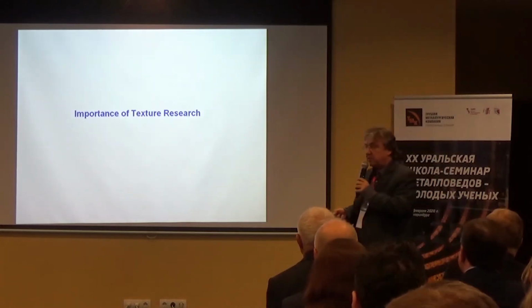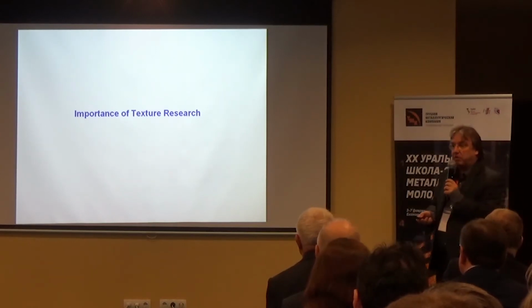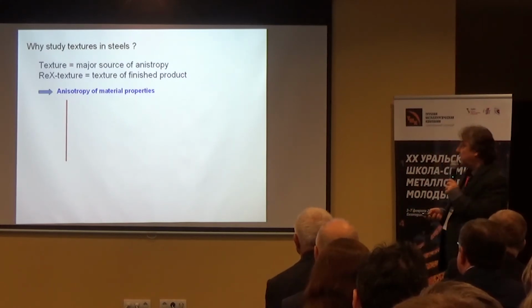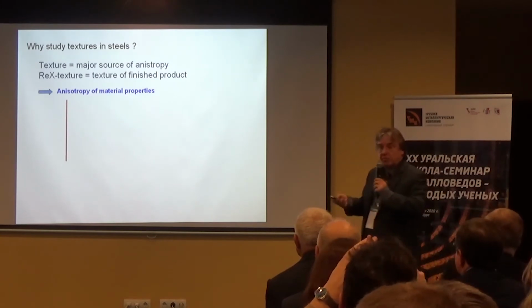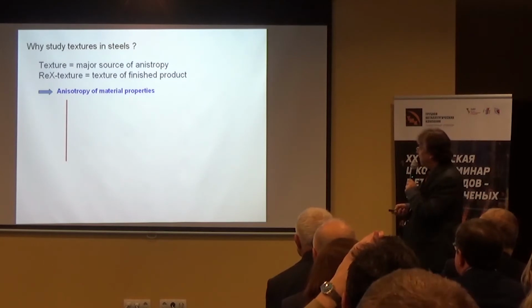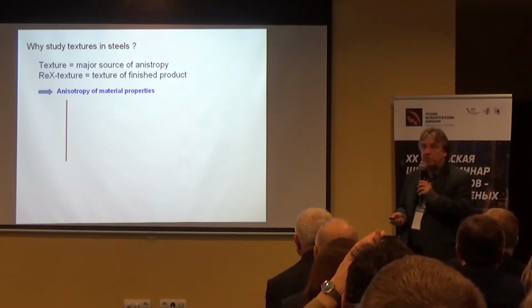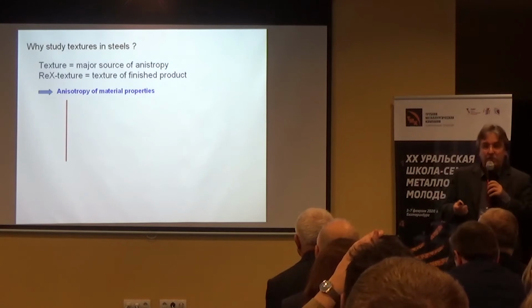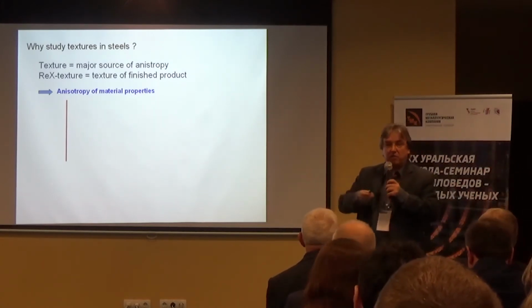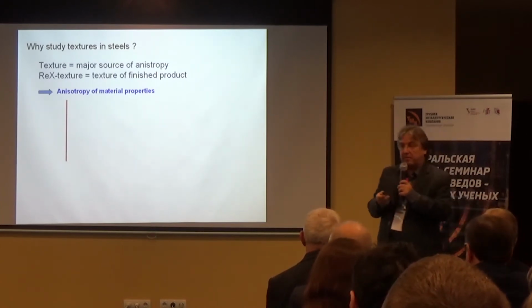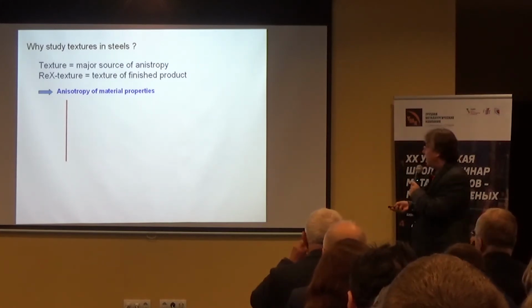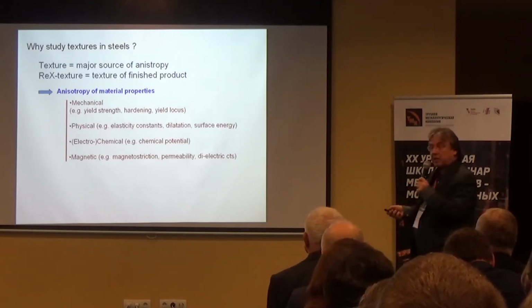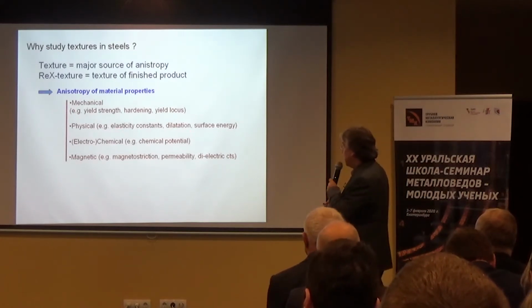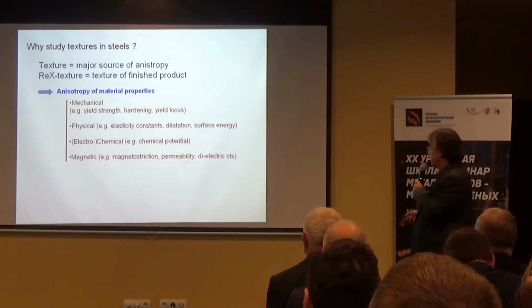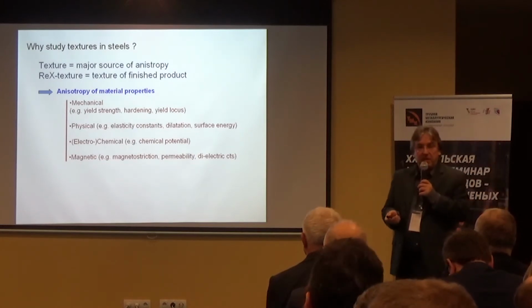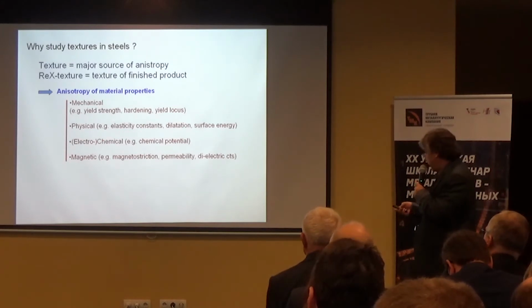Let me first start out with illustrating what is the importance of texture studies. Why do we still study texture in steel? Or in other metals, of course. Texture, in the first place, is a major source of anisotropy. So very often material properties have anisotropic behavior. If you, for example, measure the strength in the rolling direction of a steel sheet, it will be different in the transverse direction. And very often texture has something to do with this. I give here a number of examples. Mechanical properties, of course, probably the most familiar, but also physical properties such as elasticity constants, dilatation, surface energy. All this may be anisotropic properties or chemical magnetic properties.